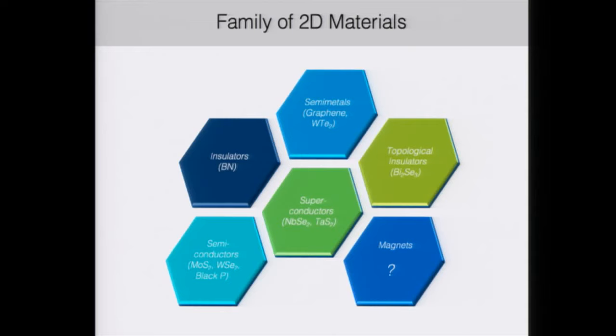The family of 2D materials has really expanded since graphene was first isolated in 2004. Now, in addition to graphene, we have other semimetals such as tungsten ditelluride. We have insulators like boron nitride. We have a long list of semiconductors, including molybdenum disulfide, as well as superconductors like niobium diselenide. And we even have topological insulators that can be exfoliated, such as bismuth selenide. However, until just a few years ago, one notable absence from the family of 2D materials was magnets.